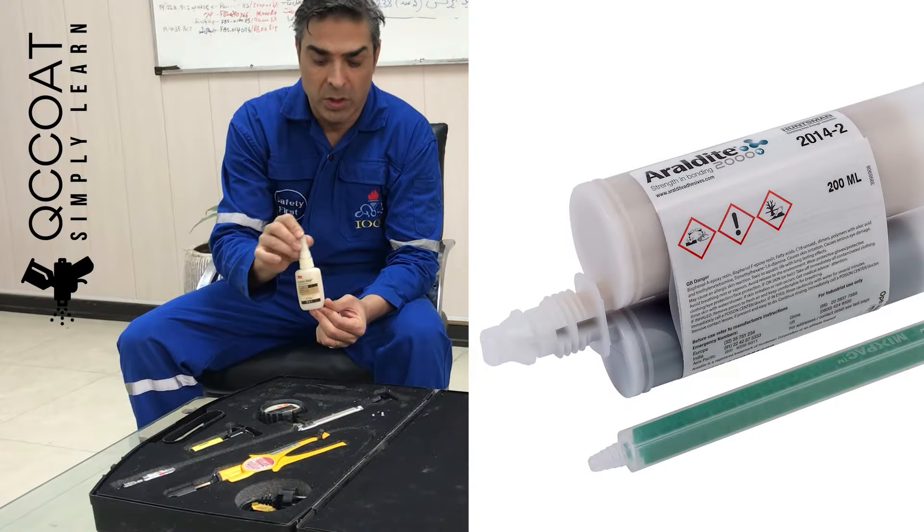The temperature of the laboratory for the test should be 21 to 25 degrees Celsius and the humidity should be between 45 and 55%. At least six tests should be done for the measurement area.